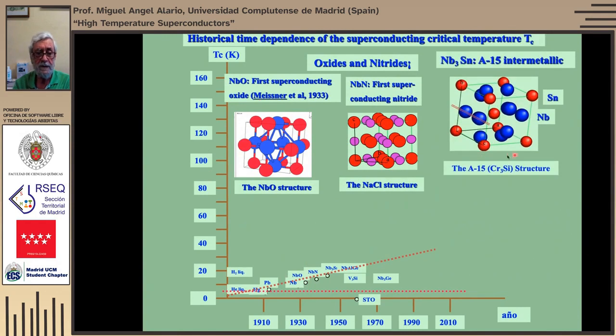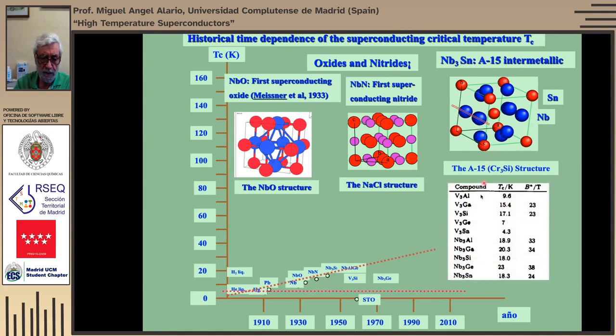Then an important discovery was the A15 structure, which was found in another area, but in fact, many materials with this structure are superconductors. We have a whole list here of materials. All of these have the same structure, which is also called the beta tungsten structure, but it was actually an impure tungsten that had it. And so these materials are very important.